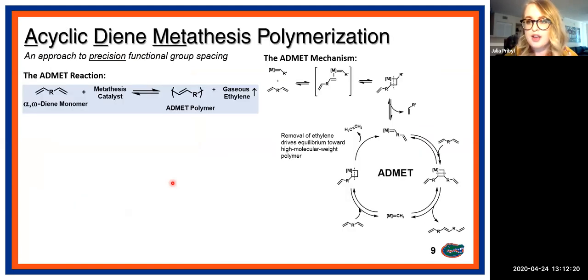So now I'll move on to the ADMET reaction. This is what we're going to talk about for the rest of the presentation. At its core, it's an approach to preparing precision functional group spacing polymers. So we start by combining an alpha omega diene monomer, where the R group can be almost countless things, and we're going to talk about a few of them in this presentation. And you put that with a metathesis catalyst. And what you get is an ADMET polymer, which has an internal olefin that we can remove later on or keep depending on what we're interested in, and gaseous ethylene are the two products.